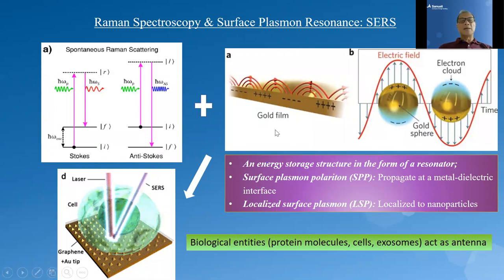On Raman spectroscopy — I presume the majority of you are familiar with what the Raman process is. At the core it is a form of interaction between photons and phonons. The key advantage is that phonons have only allowed wave numbers or energies. Therefore, by analyzing the spectrum of the scattered photons, we can backtrack into what the material we're looking at is. Combined with surface plasmon resonance, a Raman signal can be amplified by orders of magnitude — therefore we call that surface-enhanced, so it's SERS.